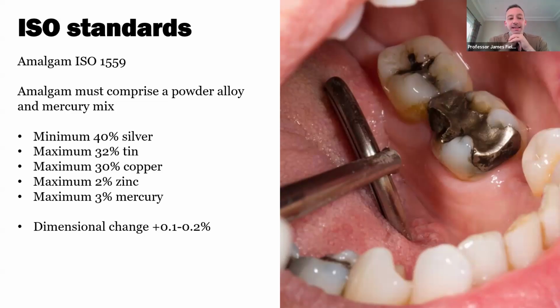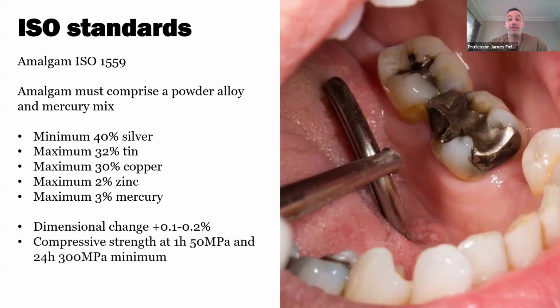And what the ISO standards said is that there had to be limits to the dimensional change that could happen with amalgam during its set and thereafter. And it also had to develop a certain amount of strength at 1 hour and then also at 24 hours. And we'll all be aware, when we used to use amalgam, of finishing it and then telling patients to be careful on the restoration for the rest of the day or until the next day. And that's because it was going through its kind of second phase set. And also there's a requirement for the material not to change dimension or to creep more than a certain percentage as well, because amalgam did do this to a certain extent.